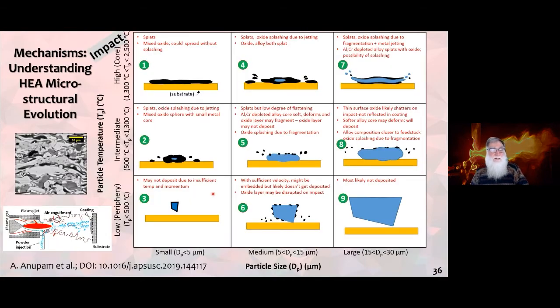Very interesting. And then if you go into more and more detail, you can plot a map of particle size, small, medium, and large, with regards to temperature, low, medium, and high. And you come up with some quite simple physical models of how we get splat behavior. Whether you've got oxides shown as dark, or you get something which is not oxidized, and I say not oxidized in inverted commas, something which retains mostly the original chemical composition. And that's published in the paper, which is indicated by the DOI down the bottom.